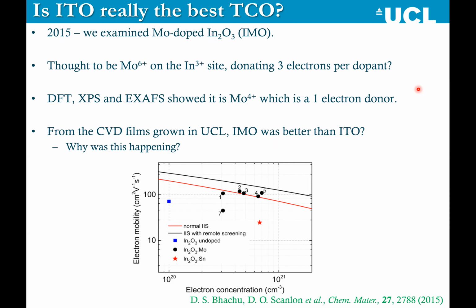And what we realized was that people believe that in indium oxide, where indium is 3+, molybdenum was thought to be incorporating as molybdenum 6+, donating 3 electrons per dopant. Now, this didn't sit well with us, because normally if you have a system where you're donating lots of extra electrons per dopant, you get killed by something called ionized impurity scattering, where all of these extra electrons are zipping around in your material, colliding with the actual atom that they've come from, and this causes ionized impurity scattering, which lowers your mobility.